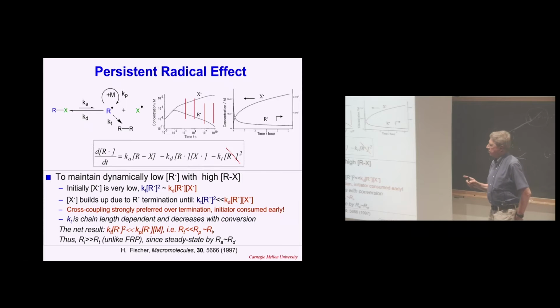So one interesting issue is really the so-called persistent radical effect. Because for many years, it was a puzzle how you can control this polymerization with nitroxide. Some people assumed that there was no termination of radicals, but in fact, it was a very different process because you have a bond which is broken homolytically. This can terminate, but this is a persistent radical, and it cannot terminate. So it would progressively accumulate. At the beginning of the reaction, you will form both the propagating radical and this capping radical. And at a certain moment, once you have a sufficient concentration of radicals, they would start terminating, decreasing their concentration, and the other one will increase, because the product of concentration of this X dot and R dot should be equal to RX concentration.